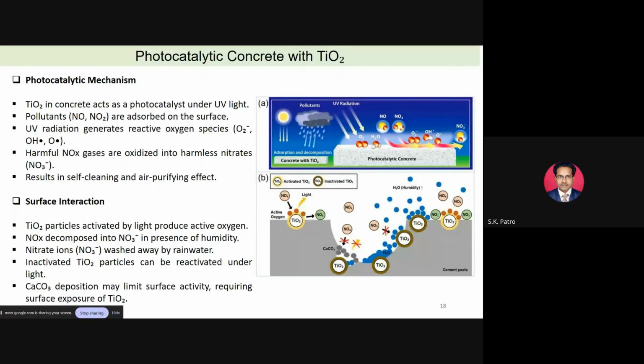when it is coming in contact with the calcium carbonate. That whitish calcium carbonate doesn't allow the contact of ultraviolet with the TiO2. When the ultraviolet doesn't contact the TiO2, the NO layers inside are unable to clean out. That's why, only when it comes in contact with the ultraviolet radiation and sunlight does it work as a self-cleaning activity. Otherwise, the CaCO3 deposition limits the surface activity. But to have a surface activity, the surface has to be exposed, with TiO2 in contact with the ultraviolet and light.